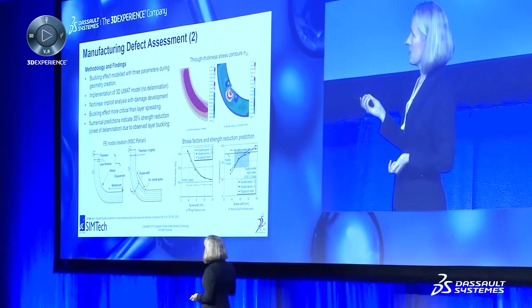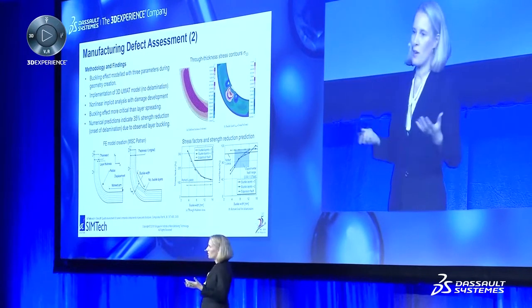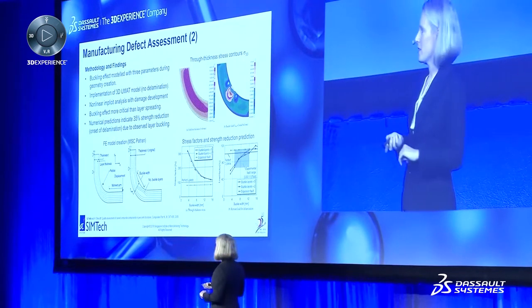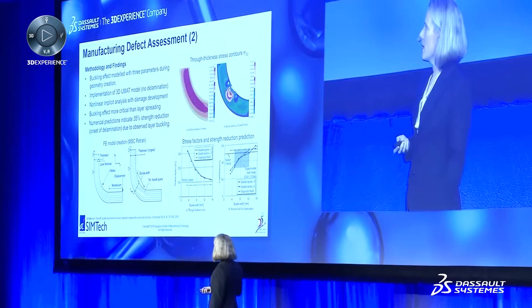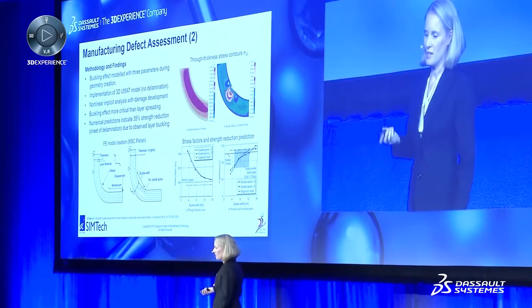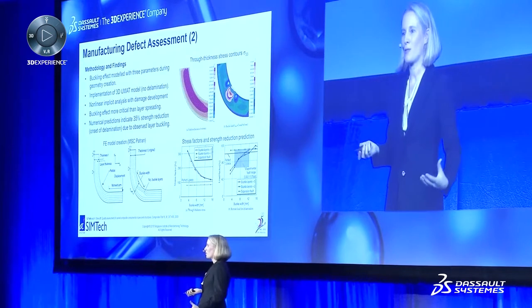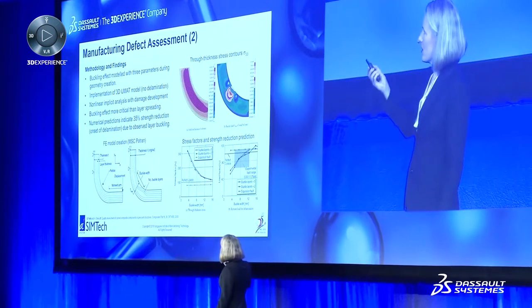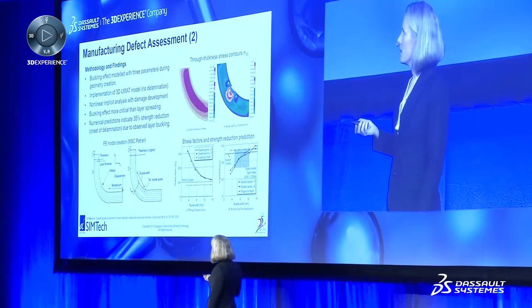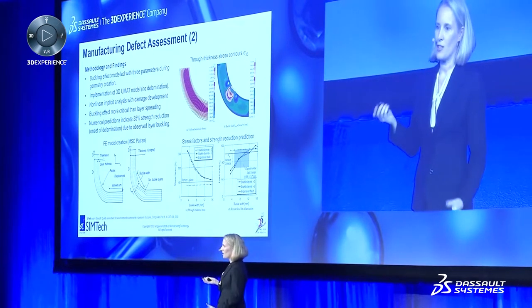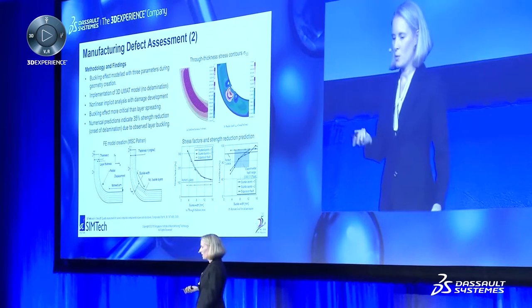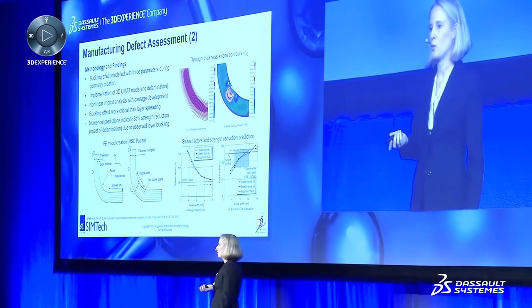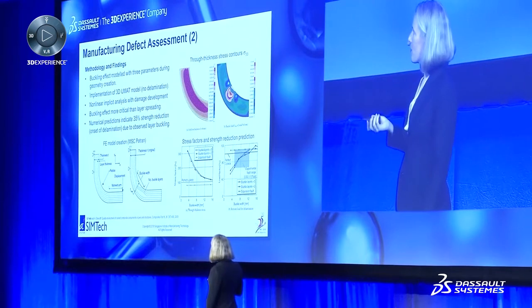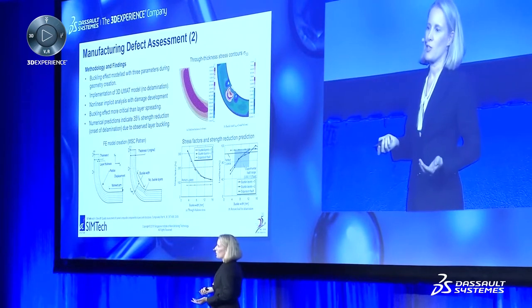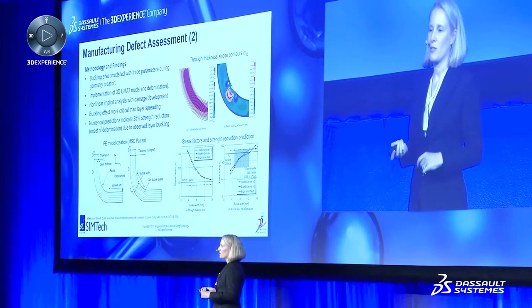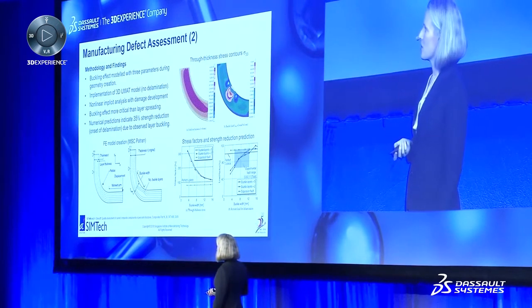And we basically did a study, and this would not have been possible experimentally, where numerically we varied the number of layers in the wrinkle and the wrinkle widths, and we looked at the stress factors, stress intensity factors, so to speak, that were being created compared to the perfect piece. And it was very obvious that even within the manufacturing defects we were seeing, if there were wrinkles present, then we could actually get a strength knockdown of up to about 25%, 30%, and that agreed very well with what we saw in the experiments as well. Layer spreading in comparison was actually not that critical because the fiber volume fraction decreases, but the thickness increases, so it kind of compensated for it.